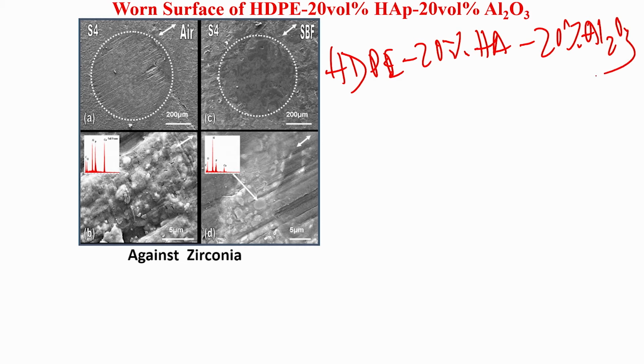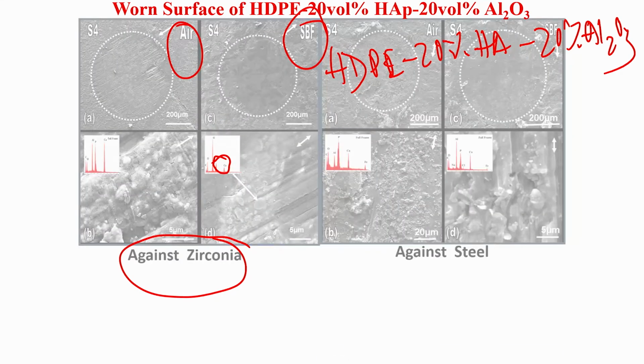Now, what you notice here in the ambient conditions and SBF simulated body fluid, when you use zirconia as a counter body, the severity of abrasive scratch wear is certainly reduced. In zirconia you will also see hydroxyapatite particles here, and the EDS compositional analysis spectra show peaks of calcium and phosphorus because of the hydroxyapatite phase which is present.